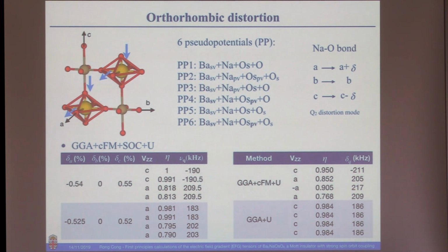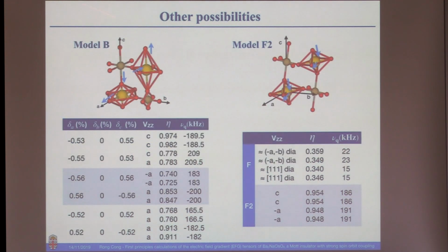Okay. And besides this, we also see another 2 models which also fit, but not as well as the first one. Firstly, there are 2 structurally distinct sodium atoms, and another one is the distortion we found in the earlier case with the Glazer type of distortion, but the main contribution to matching the experimental value comes from the magnitude of the first type of distortion.